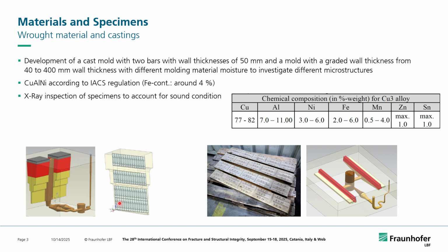The chemical composition was composed according to the IACS regulation, which is one of the standards for the design of ship propellers. And we have in the main part copper up to 82%. We are talking about aluminium in the range of 7 to 11%. We have some nickel, we have some iron, and especially the iron is a topic where we will later on see that we have also corrosional effects on the specimens.